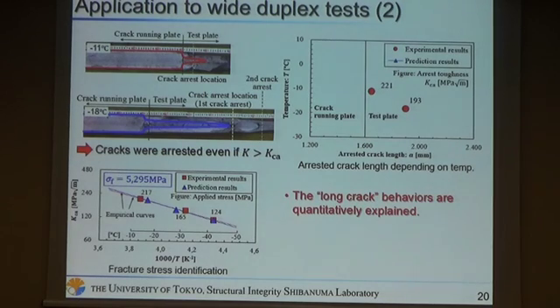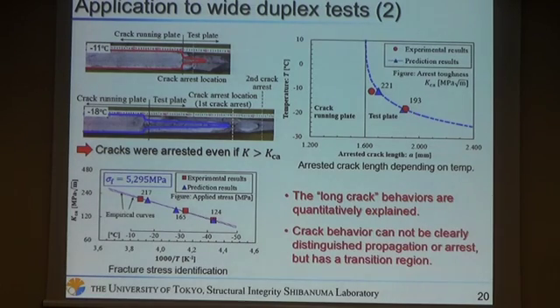We can see the long crack behaviors are quantitatively explained by the proposed model. And the prediction results of the arrested crack lengths at various temperatures are shown in this graph. From these graphs, the crack behavior cannot be clearly distinguished as propagation or arrest, but has a transition region, as in this figure.